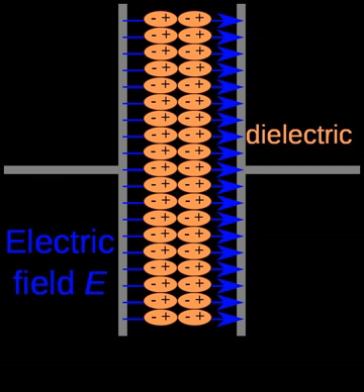This work improved tunability of bulk barium strontium titanate, which is a thin film enabler for electronics components. In a 2004 research paper, ARL researchers explored how small concentrations of acceptor dopants can dramatically modify the properties of ferroelectric materials such as BST. Researchers doped BST thin films with magnesium, analyzing the structure, microstructure, surface morphology and film, substrate compositional quality of the result. The Mg-doped BST films showed improved dielectric properties, low leakage current, and good tunability, meriting potential for use in microwave tunable devices.